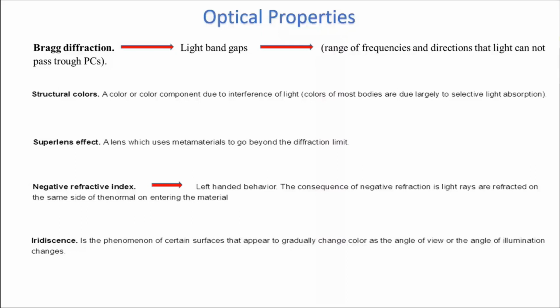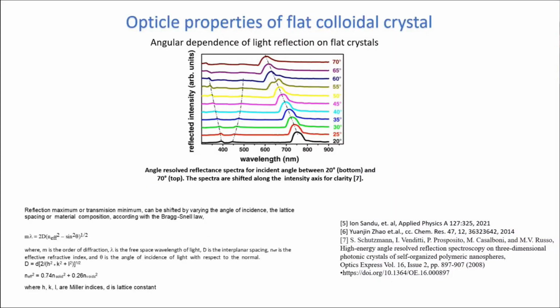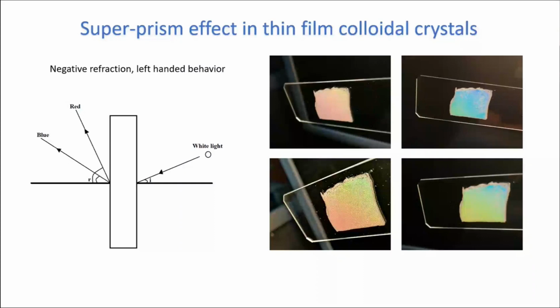These colloidal crystals, by Bragg diffraction, show a different color for a different angle of incidence of the light. And if we perform UV-Vis spectroscopy, we can see how the reflection maximum, or minimum if it's in transmission, shifts with the variation of the incident angle. We just see different colors at different angles. This is the superprism effect in some colloidal crystals fabricated by us.